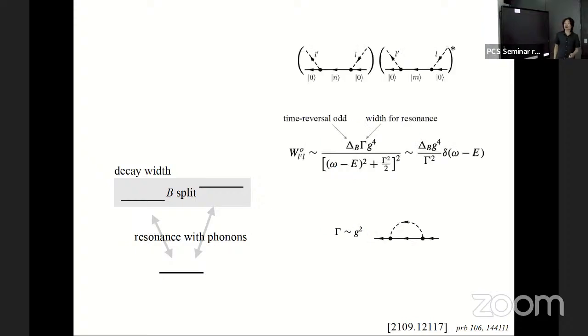And we can roughly see why. To calculate the skew scattering probability, you compute the amplitude and look at the resonance component, so probability is amplitude squared, right? And the interference comes from the intermediate state being a different defect state. So the N state, for example, is this one and the M state is this one. So that's the interference in the computation of the quantum probability. And then if you do a dimensional analysis, you'll find, first of all, it should be proportional to the time reversal odd parameter, which is the magnetic field split of the energies.